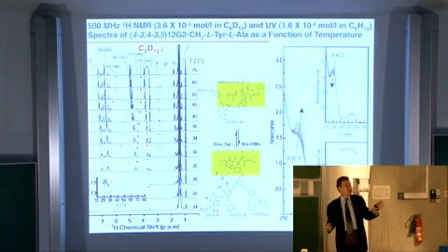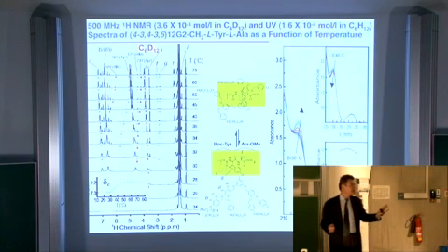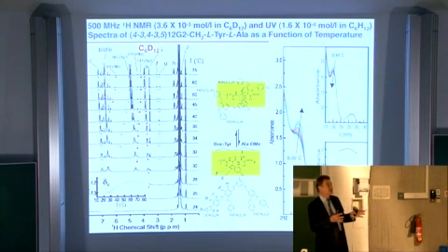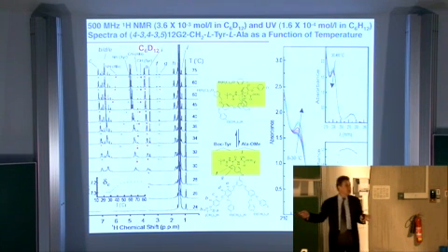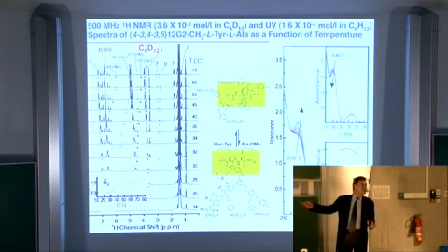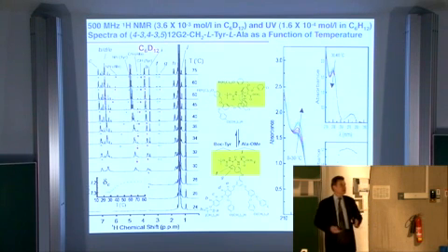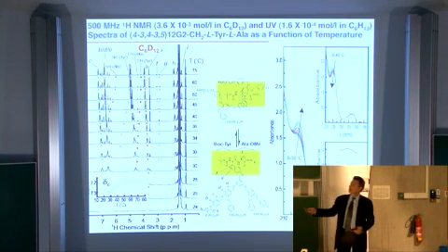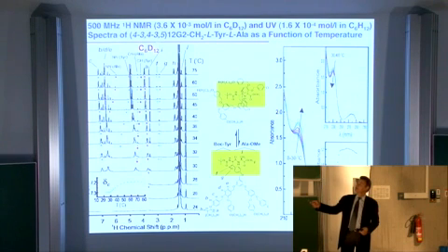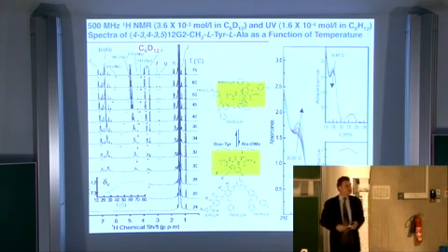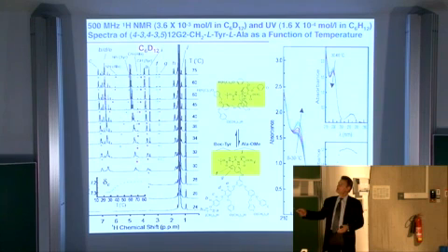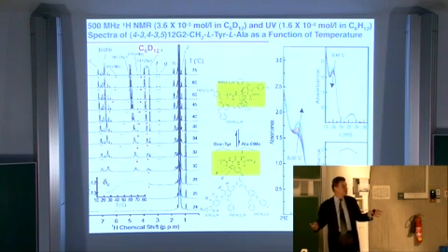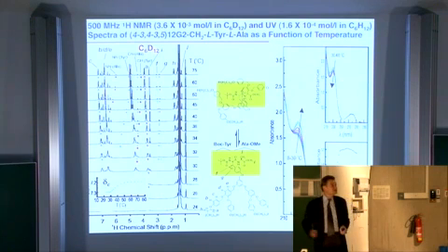So we are looking by NMR spectroscopy at a very simple series of experiments. We try to find solvents that will take us from this dynamic equilibrium, a 50-50 ratio between trans and gauche conformers of the benzyl ether, that creates a globular conformation, into an all-trans. So that's folding of the benzyl ether. We look at a lot of different solvents and dilute concentrations of this molecule in organic solvents. And when there is no change in the NMR spectrum as a function of temperature or concentration, it means we are dealing with this conformation.